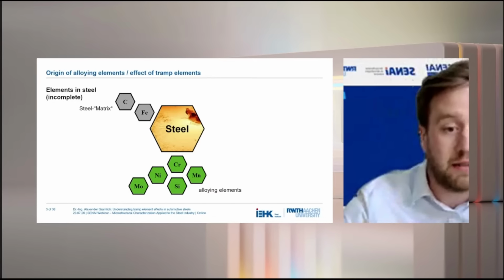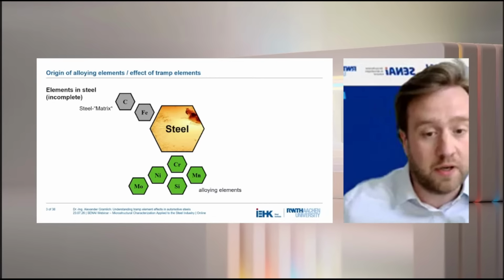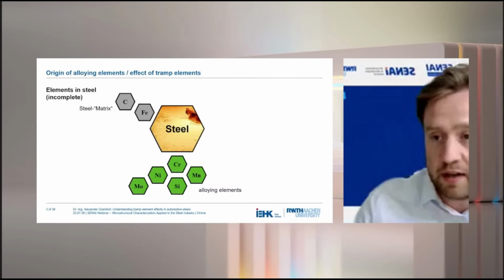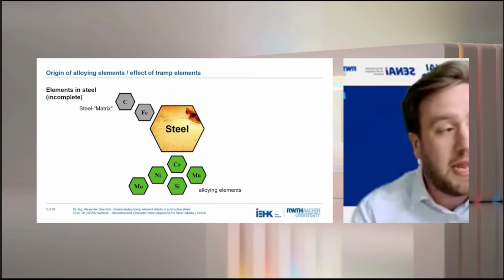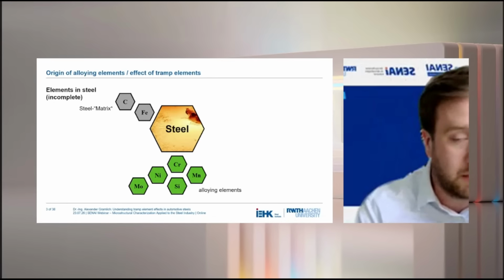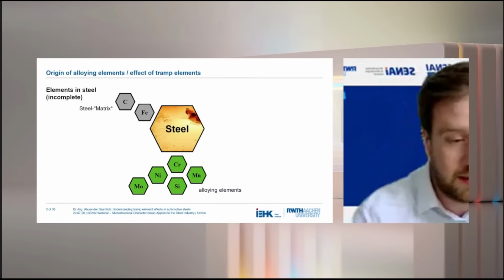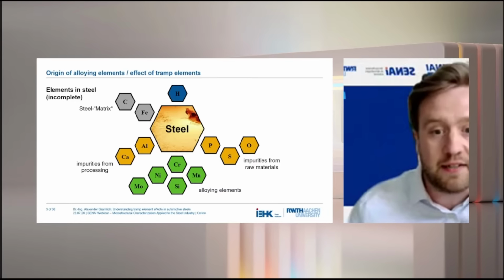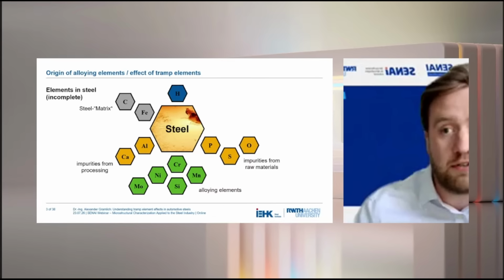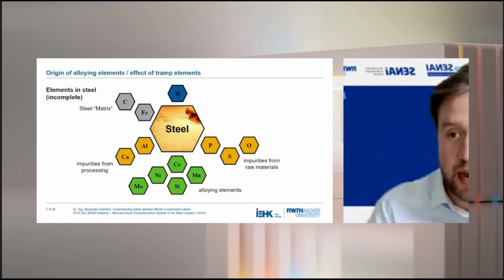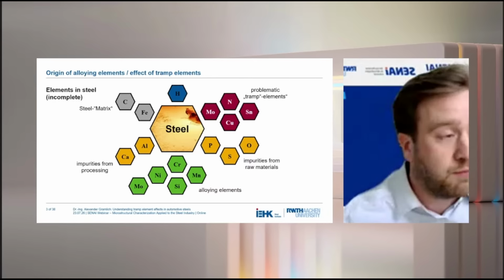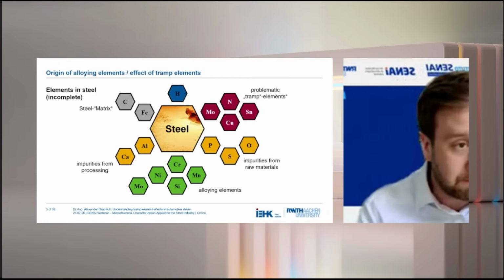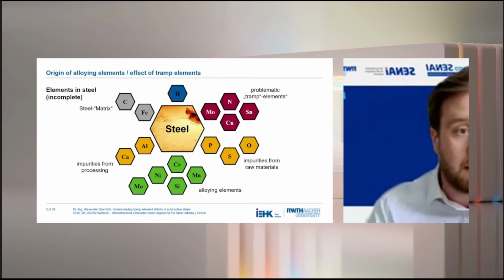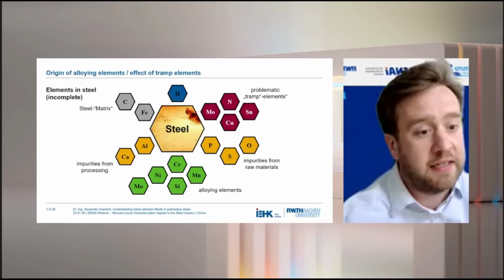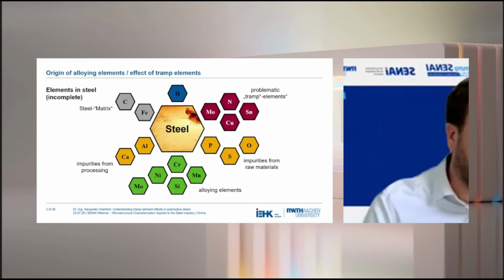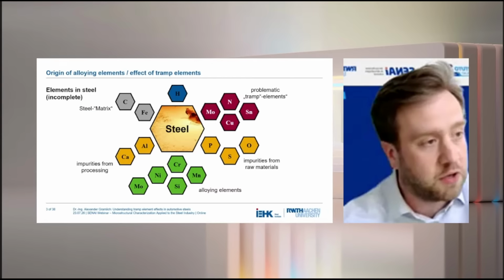So we have our alloying elements like chromium, manganese, nickel, silicon, and molybdenum. And every one of these alloying elements is always added with a specific aim in mind: to increase strength, ductility, whatsoever. Besides these wanted elements, we also have impurities, either from processing or from raw materials. Also, we always have a certain amount of hydrogen in our steels, but most problematic are the so-called tramp elements. And the group I'm showing here, like copper, molybdenum, and so on, they are more problematic than the impurities from raw materials because it's really difficult to extract them from your liquid melt.